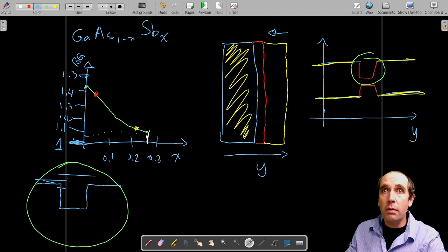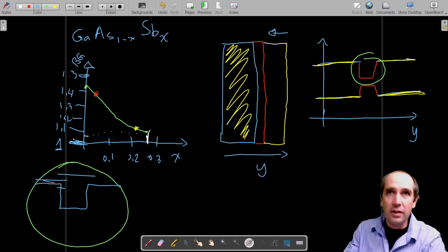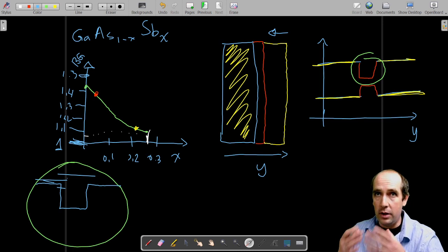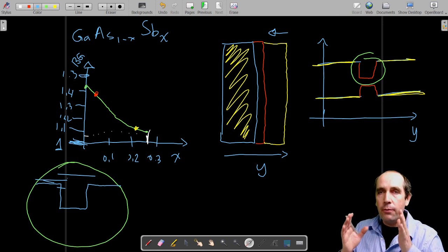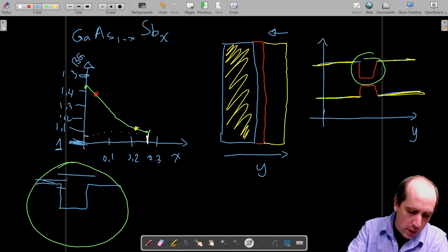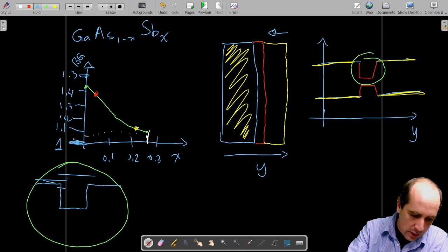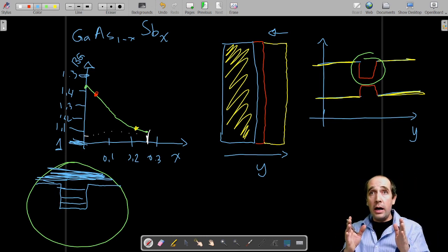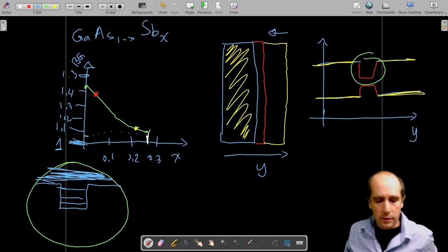And this will produce additional quantization. So this continuum, or almost continuum of levels that are coming from the lattice potential, will be forced to be requantized. Now, instead of having a continuum of levels, we will maintain a continuum of levels in the top part, but here we will only have a series of allowed levels, which are basically the solution of the square well.